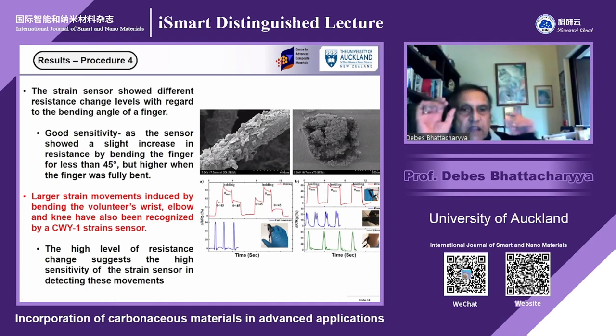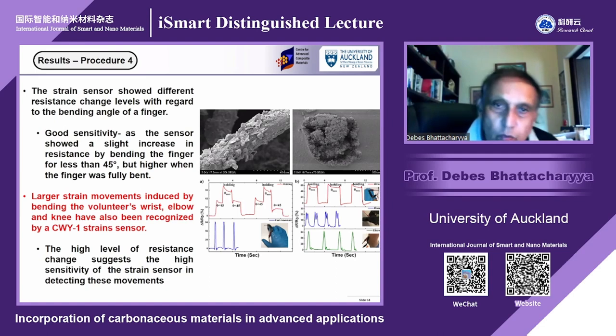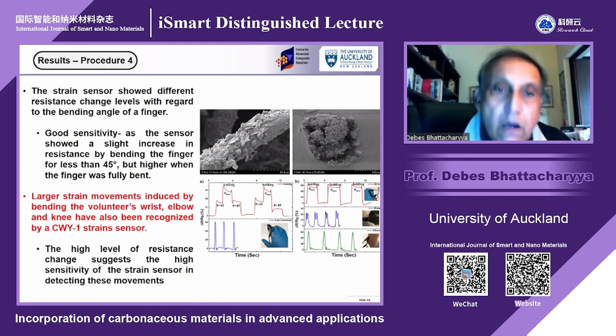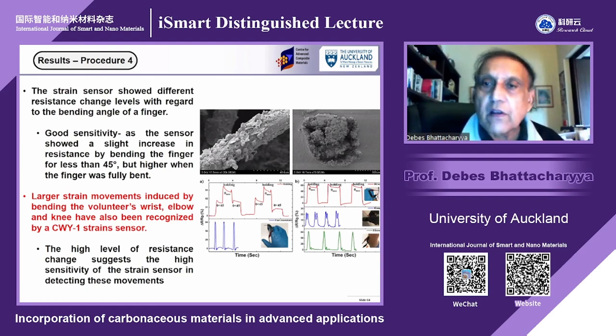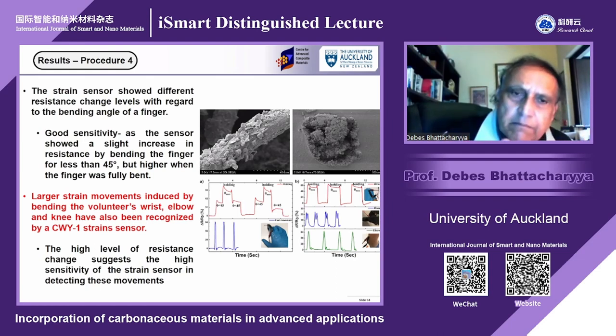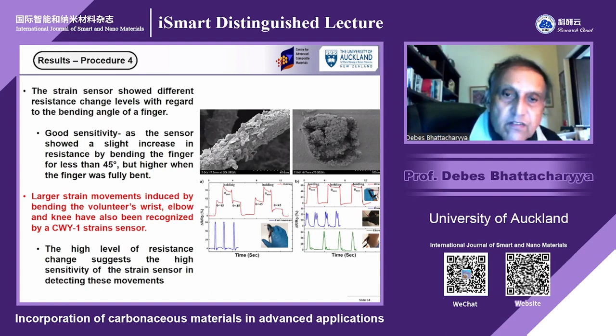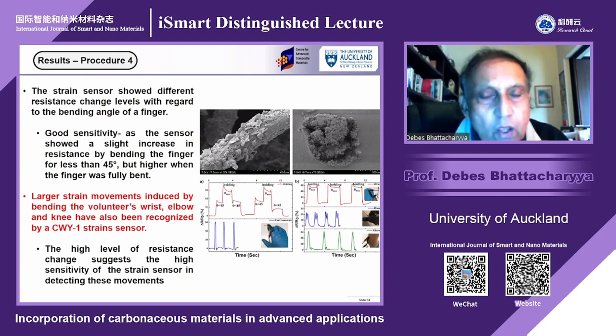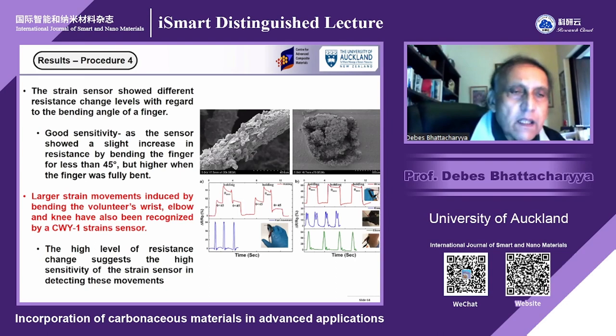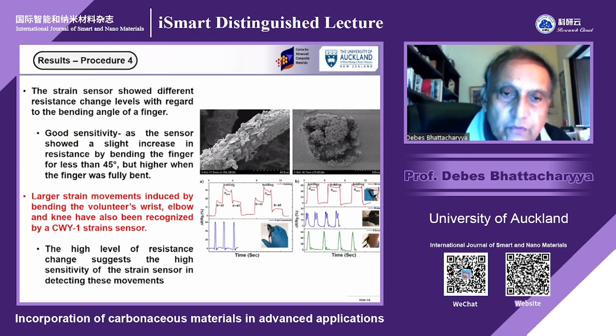And the strain, what was that? CWY1 was the straight one. So there is a hint for manufacturing. How are you going to keep that straight? Keep them under slight tension, so that all these wrinkles go. In many composites manufacturing also, we try to avoid any fabric wrinkling or pre-existing fiber wrinkling, because if there is a wrinkle, it can be the source of some kind of perturbation in the future.